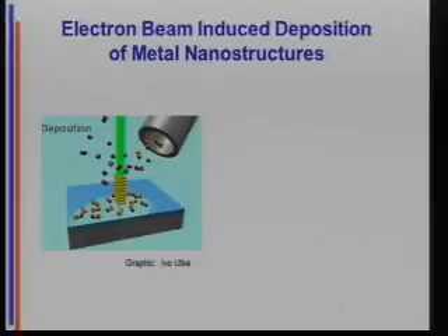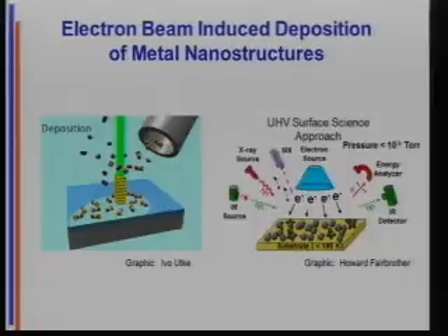The reason why this is interesting is it's kind of like 3D printing of metal nanostructures, because if you use an SEM tip as your electron source, you have 3D control of where the tip is, and you can basically just draw things in place and write metal nanostructures. Okay, but you can't do mechanistic chemistry under real deposition conditions. What we do is we work with Howard Fairbrother at Johns Hopkins, and we model this in a surface science tool. So Howard's a serious surface science person, and we do it under UHV conditions, where we deposit a monolayer of our precursor onto a substrate, and then Howard kills it with an electron gun, basically.